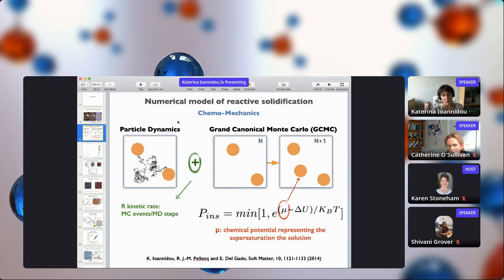To do so, we use a hybrid modeling scheme that contains a grand canonical Monte Carlo part for the addition and deletion of particles, and a molecular dynamics part that we use for the dynamics of the system and to relax the structure. We have a rate that controls how fast or slow hydrates precipitate, and we have the chemical potential in the probability of the grand canonical Monte Carlo that controls the equilibrium density of the system.